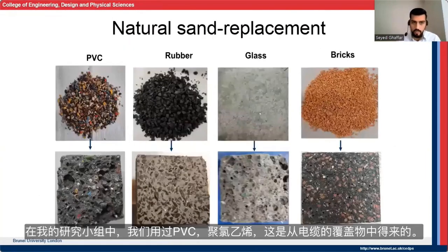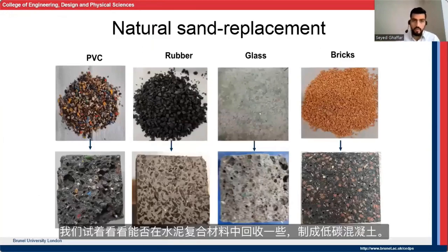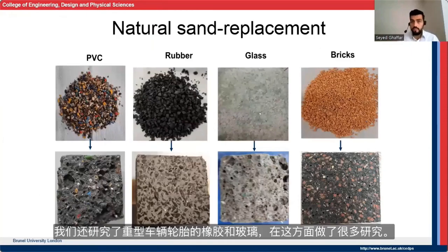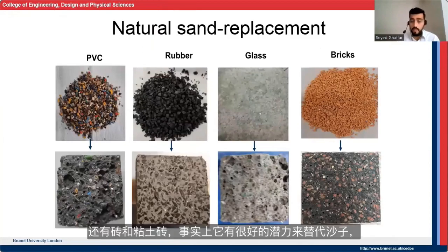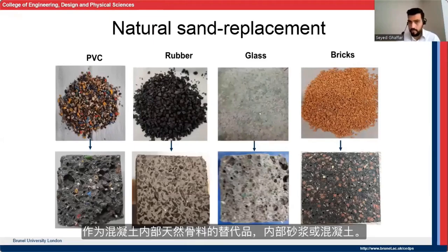And in my research groups, we have worked with PVC, polyvinyl chloride, which is coming from the covers of the cables. We try to see if we can recycle some of them in the cementitious composite into low carbon concrete. We work with rubber from tire rubbers of the heavy vehicles, glass. There's been a lot of study on waste glass, and also bricks, the clay bricks, which has shown actually to have a very good potential as a replacement of sand, as a replacement of a natural aggregate inside the concrete, inside the mortar or concrete.